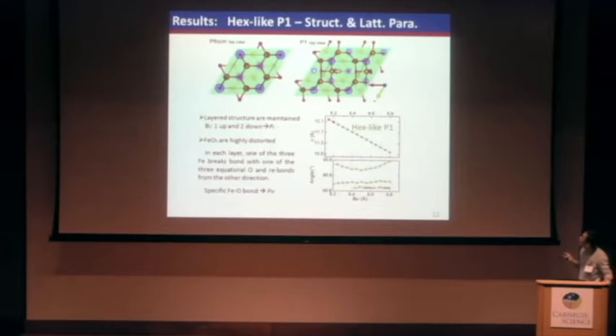The major differences come from the in-plane displacement. We can notice that in this hexagonal phase, the iron stays at the one-third positions ideally. While in this phase, we can notice that the iron and the oxygen break bond and move against each other and then rebond in another direction. Here we mark those bonds as a specific iron-oxygen bond, since it will be related to the magnetism and the polarization closely.